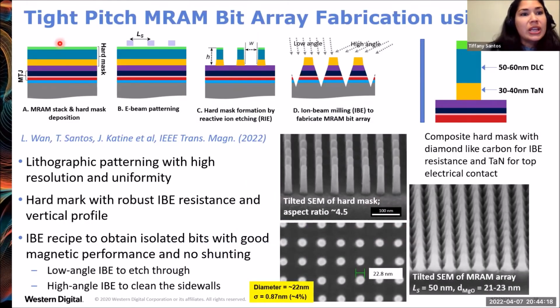Okay, so here's how we made our tight pitch MRAM bit array in our research clean room. So we started out with a blanket film of a magnetic tunnel junction, and we put a hard mask on top for the patterning. The hard mask is made of tantalum nitride and diamond-like carbon. And the hard mask was patterned by E-beam lithography and etched by reactive ion etching. And you can see that the hard mask then has this very high aspect ratio.